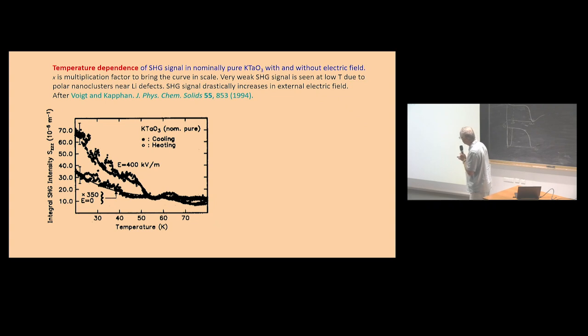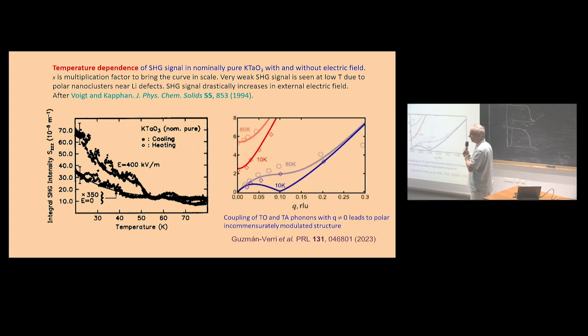There is a very weak signal in zero electric field at low temperatures, but if you apply an electric field, note it is multiplied here 350 times. So the intensity is very low, but the effect is present, and it can maybe be explained by the presence of polar nanoclusters in potassium tantalate, again like in strontium titanate, when you have coupling of the optical branch with the acoustic branch, which produces a theoretical minimum at non-zero Q vector, and it finally produces some modulation